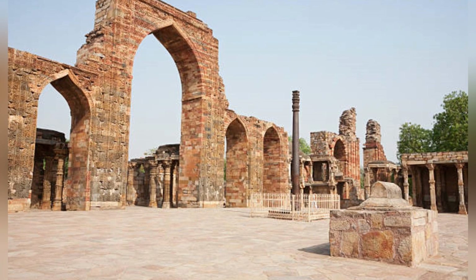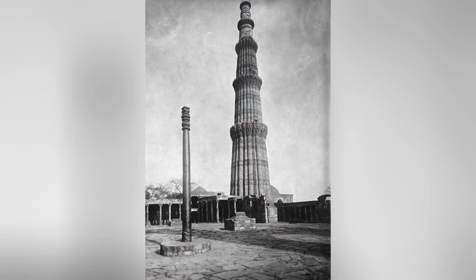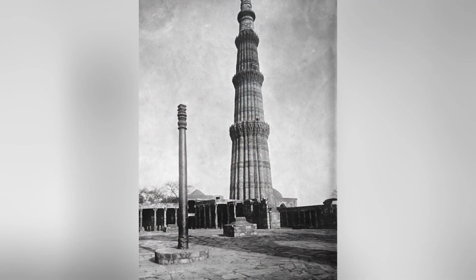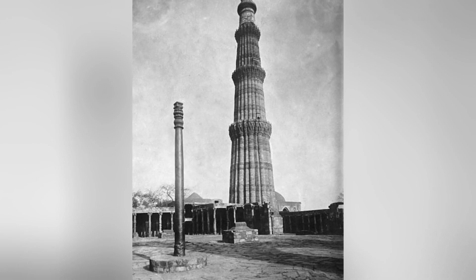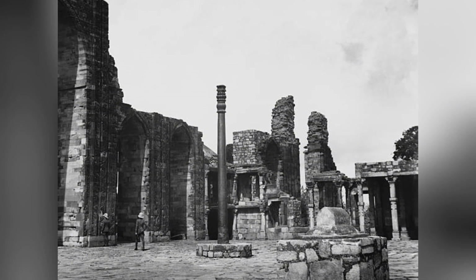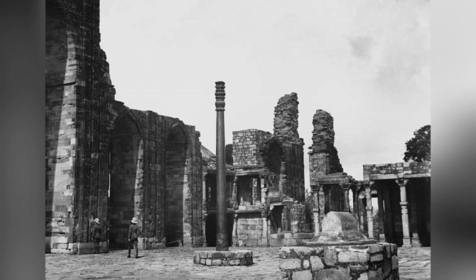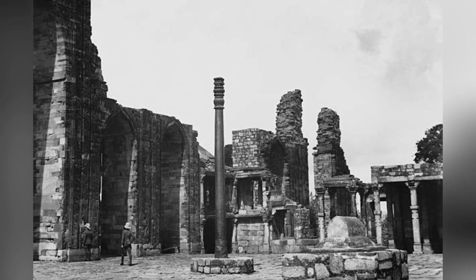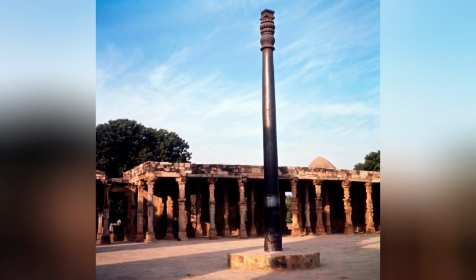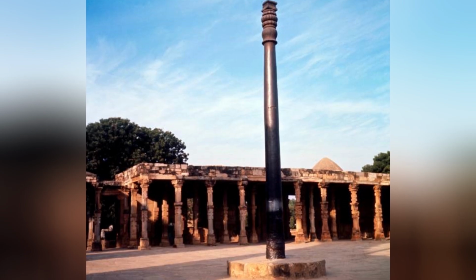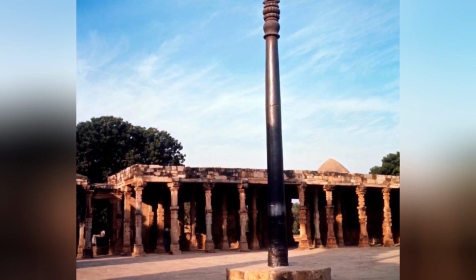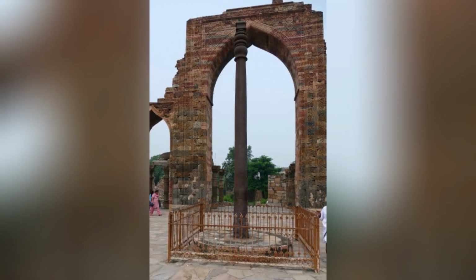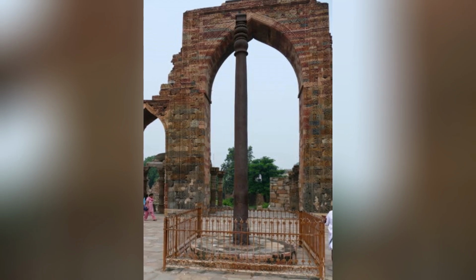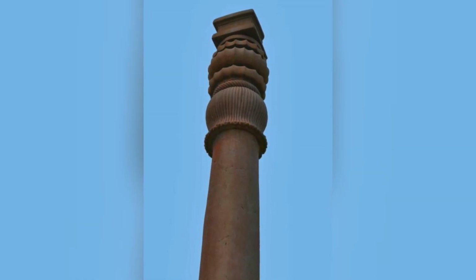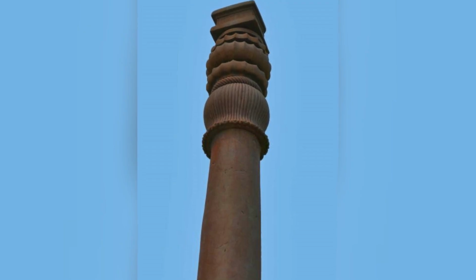The surface inscriptions on the pillar have been studied not only for their historical content, but also for the information they provide about the surface condition of the iron at the time the inscription was carved. The depth and the sharpness of the letters indicate that the iron was relatively soft and relatively uniform when the inscription was carved, consistent with the low carbon content and the high purity of the bloomery iron. The preservation of the inscription over 16 centuries, with the letters still sharp and legible, is one of the most compelling visual demonstrations of the pillar's corrosion resistance, because the inscription, which consists of shallow grooves cut into the surface of the iron, would have been the first feature to be obliterated by corrosion if the pillar had corroded at the rate of ordinary iron.